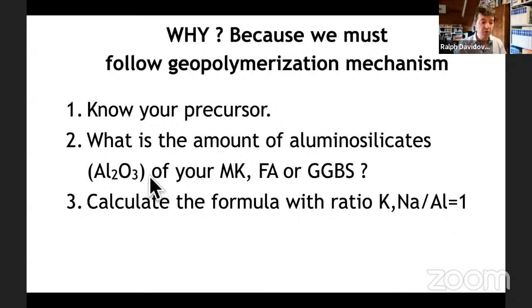Once you know the amount of Al2O3, you can calculate your formula, and respecting this ratio, sodium to aluminium equals 1 guarantees there will be no leachate or blooming of free salt, no shrinkage, no cracks with enough fillers. It will provide good chemical and structural stability. There is no formula like, let's take 40% of silica, 50% of fly ash, 10% of slag, and you're good. No. It is a very precise recipe according to the amount of aluminosilicate you have in your ingredients.